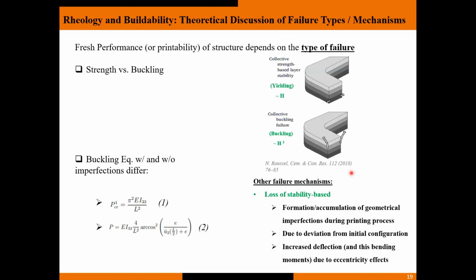You first have to overcome extrudability, then you have to overcome the yielding at the lower layers. Once you're able to print an object, then buckling is typically the common failure mechanism. So it's important to identify what rheological properties need to be controlled.